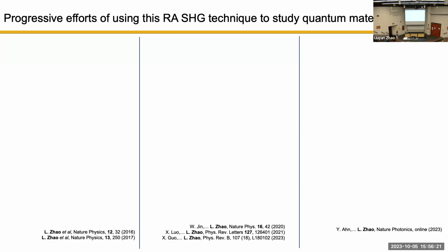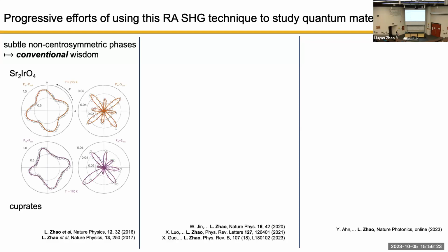So we pushed the sensitivity of the SHG technique in his group, and used it to study cuprates and iridates. There we saw an inversion symmetry breaking phase that coexists or shares a boundary with a pseudogap boundary in those compounds. But this is really still leveraging the so-called conventional wisdom. We leverage the fact that SHG sees inversion symmetry breaking. We just made it more sensitive to inversion symmetry breaking and made this progress.